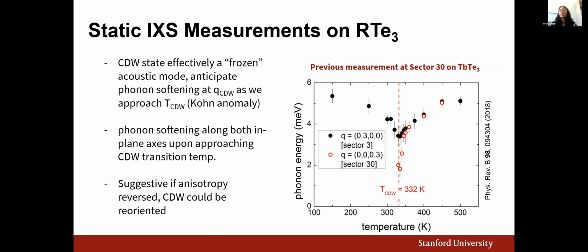Nevertheless, these observations are indicative that, above the CDW transition, CDW fluctuations are fairly isotropic between the two directions, and suggest that if we could reverse this anisotropy in this crystal, it may in fact be possible to reverse or reorient the CDW wave vector in the material. And say we could do that by applying uniaxial strain.